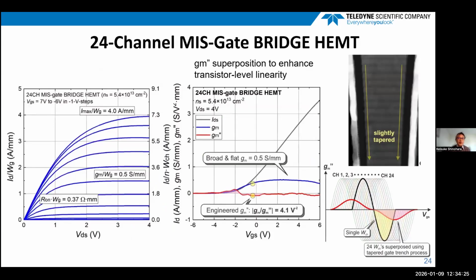This is the 24-channel MIS-gate transistor. So the number of channels increases the drain current density. Now, the maximum current density goes up to 4 amps per millimeter. And if the current density is normalized by the actual channel width, it reaches 7.3 amps per millimeter. And on the right, I show the transfer characteristics.